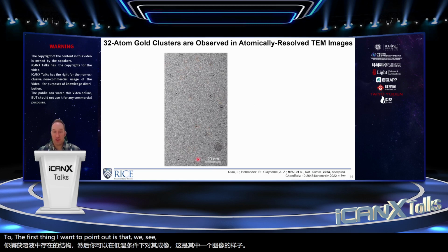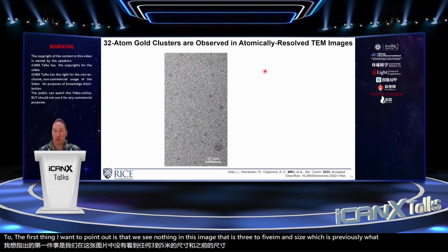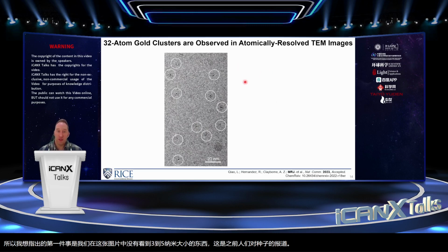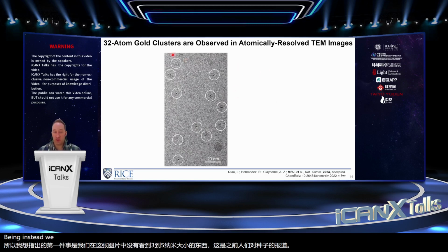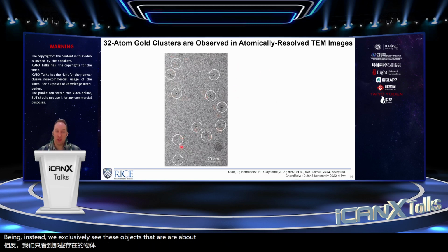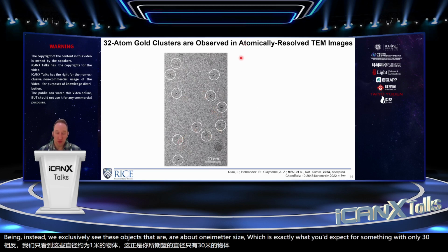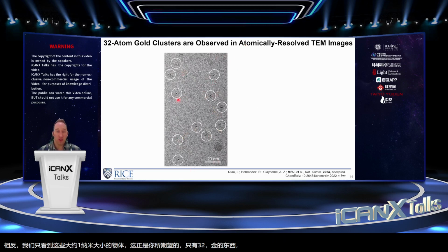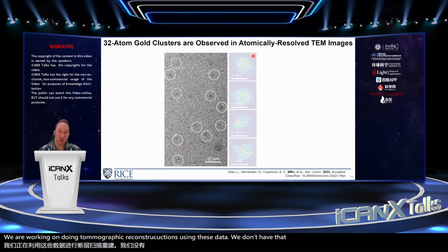The first thing I want to point out is that we see nothing in this image that is 3 to 5 nanometers in size, which is previously what people had reported the seeds being. Instead, we exclusively see these objects that are about 1 nanometer in size, which is exactly what you'd expect for something with only 32 gold atoms. We are working on doing tomographic reconstructions using these data. We don't have that working yet.